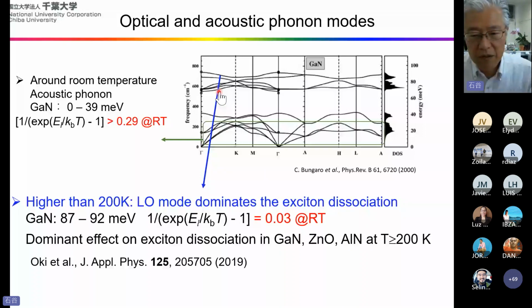Even though the percentage of existing LO phonons is very small compared to the acoustic phonons, a very small amount of these optical phonons gives a severe effect on device operation. So the control of this longitudinal optical phonon is very important.